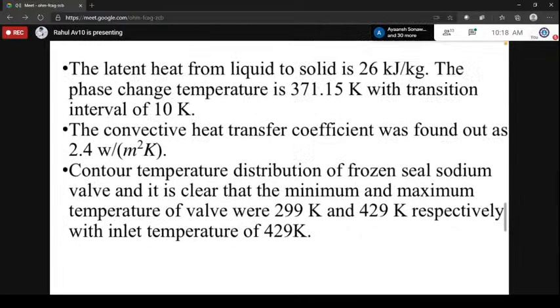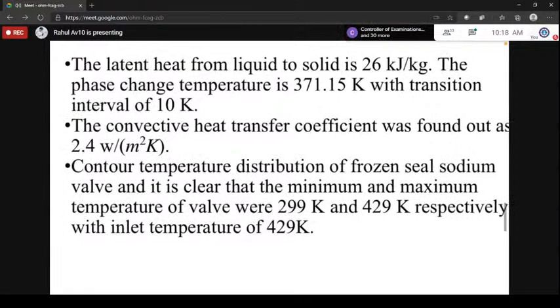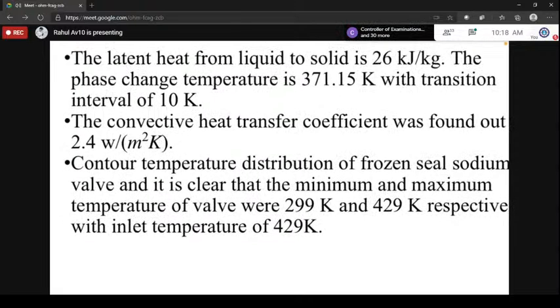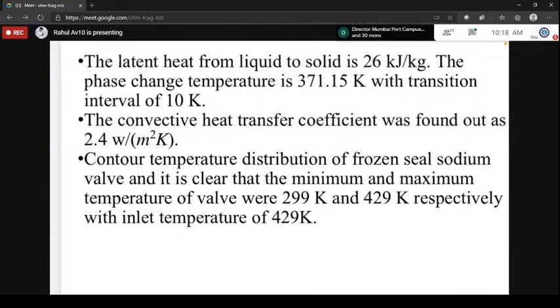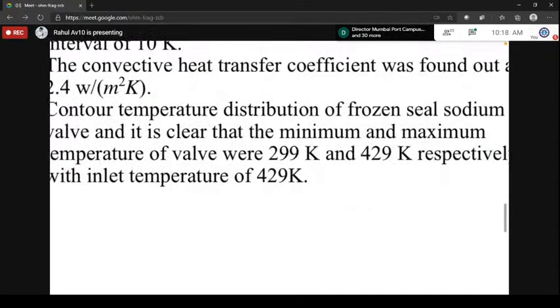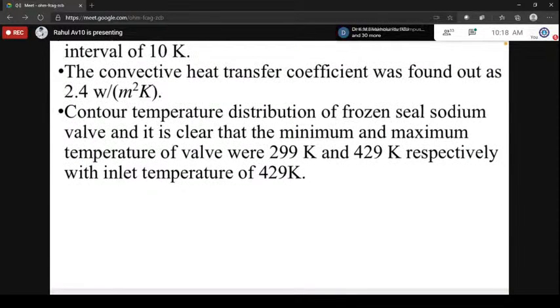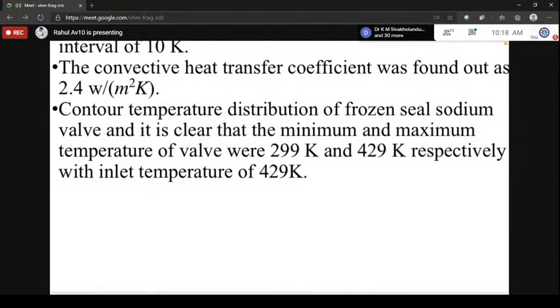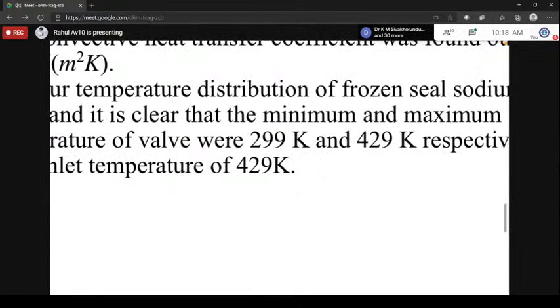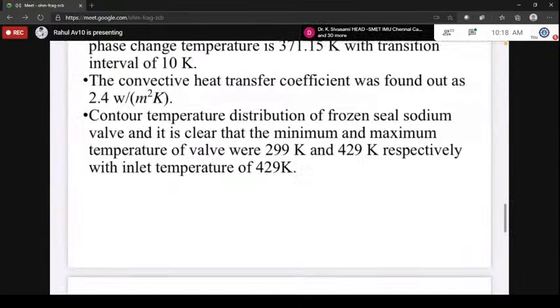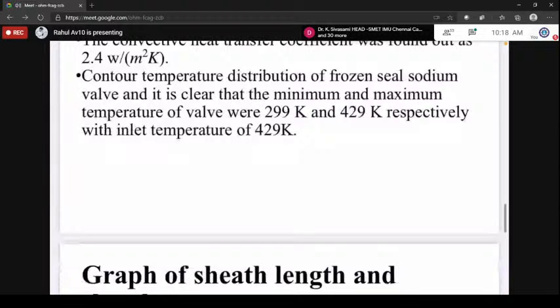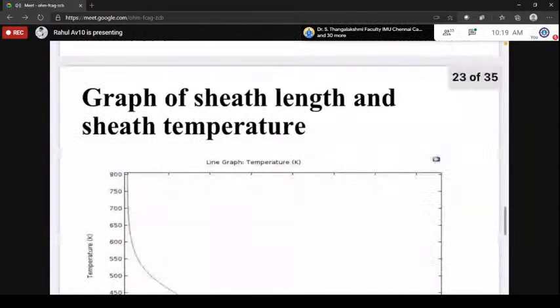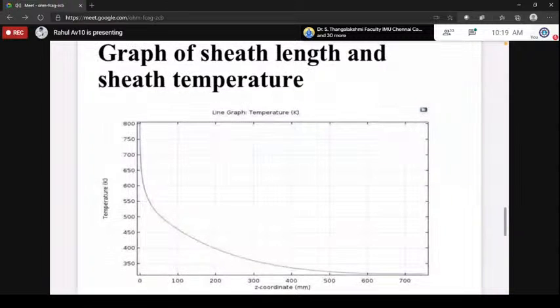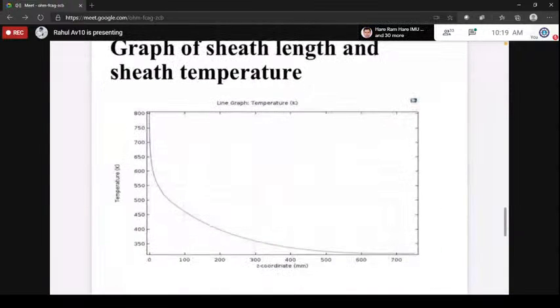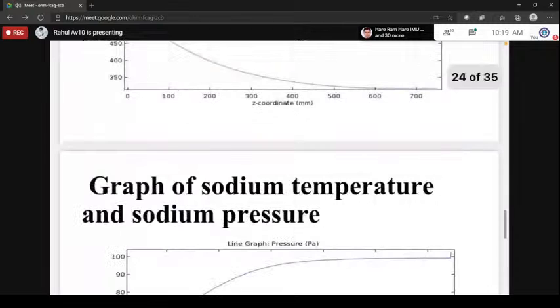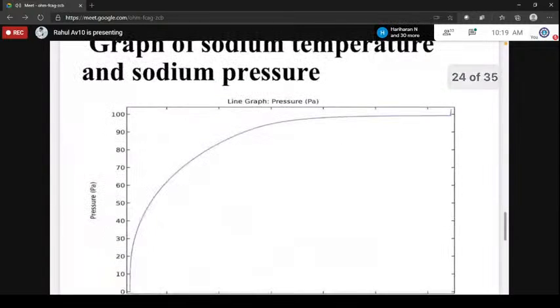But here we are getting an enhanced convective heat transfer coefficient, which is found to be 2.4 watt per meter square Kelvin, and even the maximum and minimum temperature, which are also the inlet and outlet temperature of this valve, are 299 Kelvin and 429 Kelvin, which is quite different from the previous case. And this is the graph of sheath length and sheath temperature for this second case. And this is the sodium temperature and sodium pressure graph.